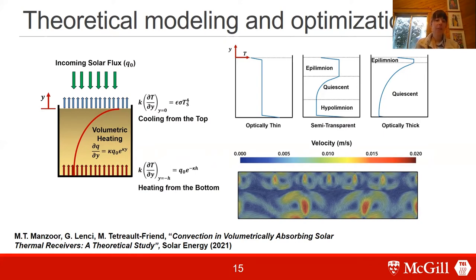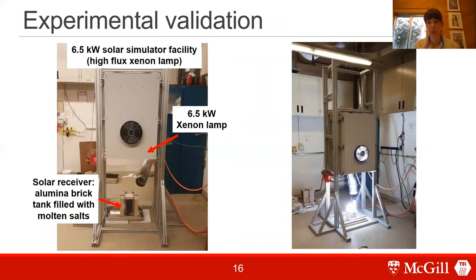So the next step for the CS pond concept is, now that we've demonstrated the concept in the prototype and we have our theoretical models, to actually develop a higher temperature CS pond concept. So at much higher temperatures using chloride salts, which can operate at above 700 degrees Celsius, so that we could pair the system with a supercritical CO2 cycle. So what we're doing now is we're conducting tests in the lab to optimize the receiver design at these higher temperatures. So first demonstrate it and then optimize it.